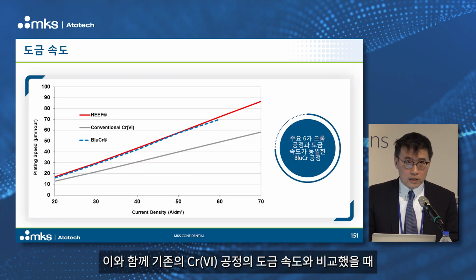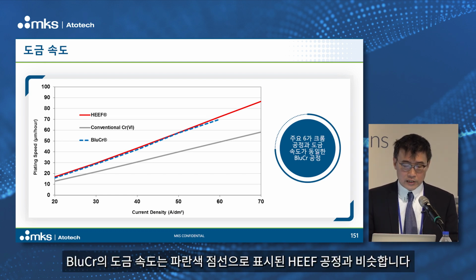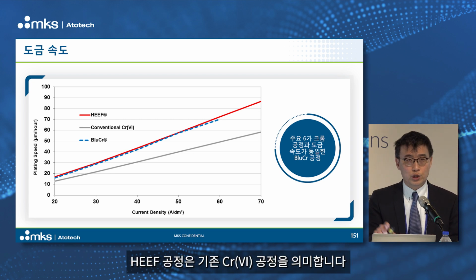And with that, when compared to the plating speed of a traditional or conventional Chrome 6 process, you can see the BluCr with the blue dotted line here. The plating speed is comparable to a normal HEEF process, which is a conventional Chrome 6 process.